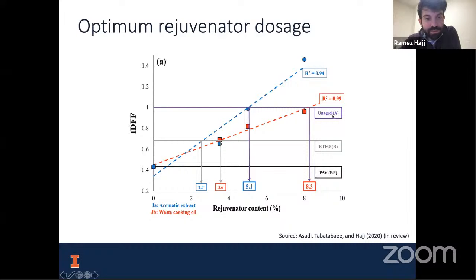This is the aromatic extract. For rejuvenator B, which is the waste cooking oil, we'll use 8.3%. And we have a very targeted choice here. So this helps take the guesswork out of what I discussed before, where we use 3 to 9%. If we only want to restore 75% of the original properties, we can use as little as 2.7% or 3.6% rejuvenator. So this is, again, quite a powerful tool for us in asphalt paving, because this gives us a lot of options to restore those original properties.